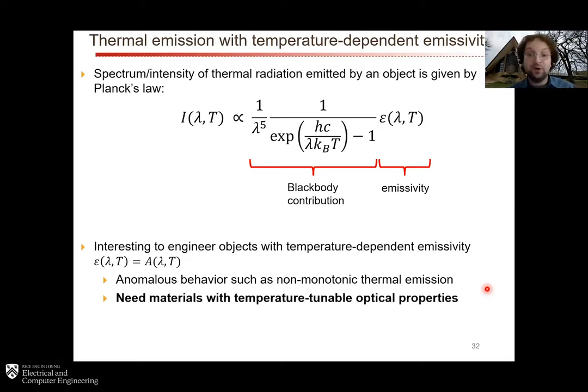And in particular, if you wanted to do something like that, you need materials that have temperature tunable optical properties that are very, very temperature tunable. So you change the temperature a little bit and your optical properties change a lot, because the blackbody contribution changes very quickly with temperature. If this is not the case, if this is, for example, a piece of silicon which is gradually changing with temperature because of filling of the conduction band, this effect is essentially negligible. You can treat the emissivity as more or less a constant. And so we need materials where the emissivity is decidedly not constant as a function of temperature.